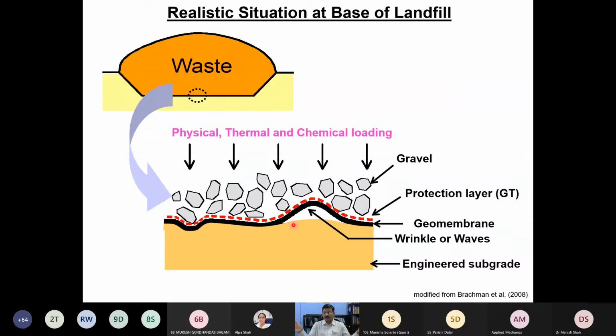These wrinkles are sometimes called waves, and even after placing the waste, the wrinkles are not really going to become flattened. The reason I am talking about this is that once a wrinkle is formed, it is a high stress concentration zone. When an indentation is formed, it is also a high stress concentration zone. The meaning thereby is, when the material is subject to a certain straining level and is exposed to the oxidation cycle, the degradation is entirely different from when the membrane is simply dipped into the leachate. As a result, we want to really see this kind of phenomenon.